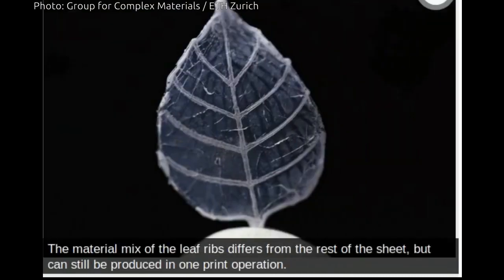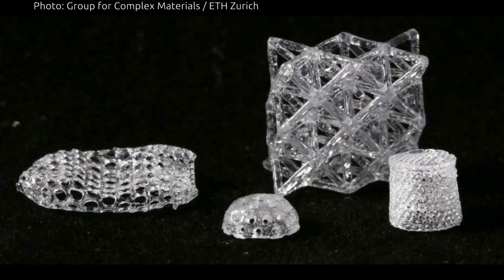The researchers can change various parameters in each layer, including pore size. Weak light intensity results in large pores. Intense illumination produces small pores. The researchers are also able to modify the microstructure layer by layer by mixing silica with borate or phosphate and adding it to the resin. Complex objects can be made from different types of glass or even combined in the same object using the technique.